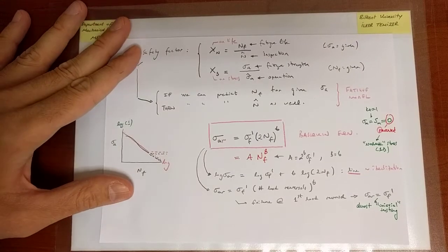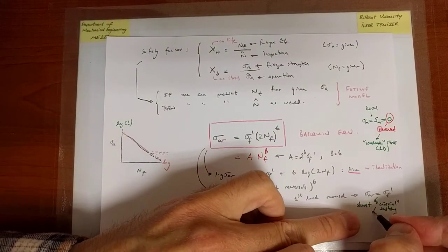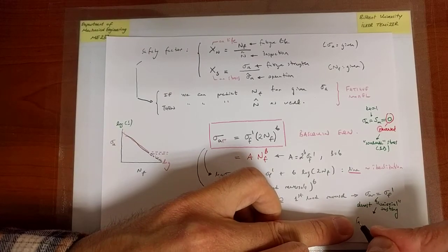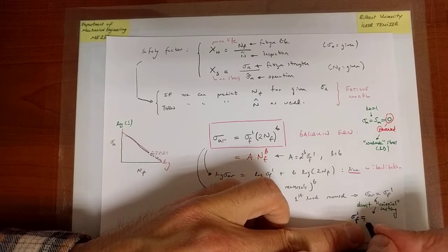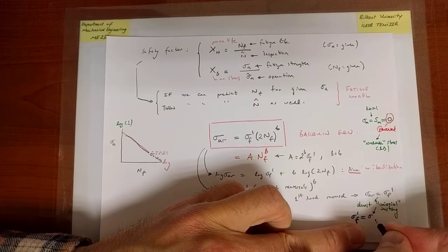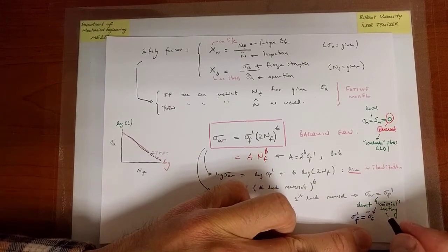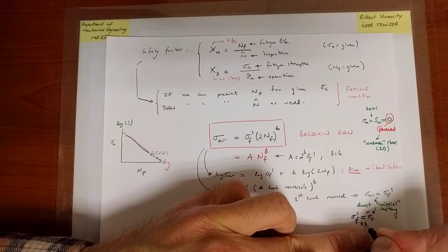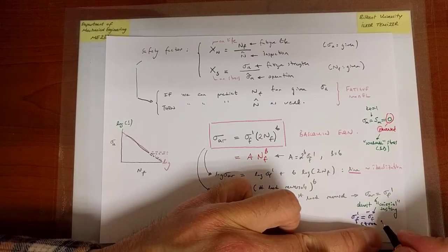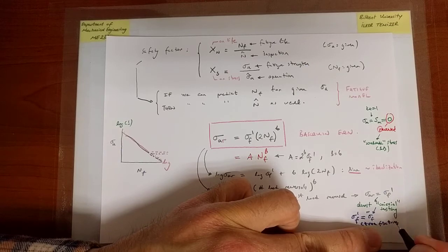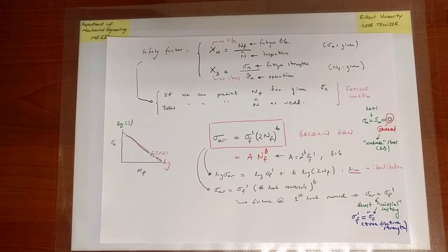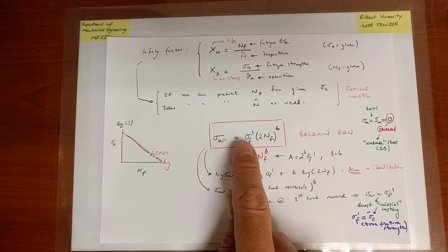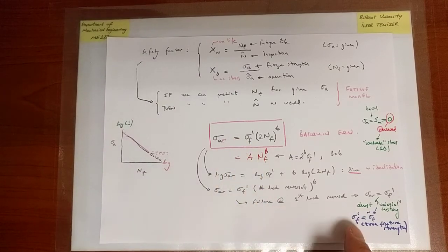It turns out one of those values, namely the fracture strength, in fact, the true fracture strength, is essentially something that is very representative of the value of sigma_f prime that appears in the Basquin equation.